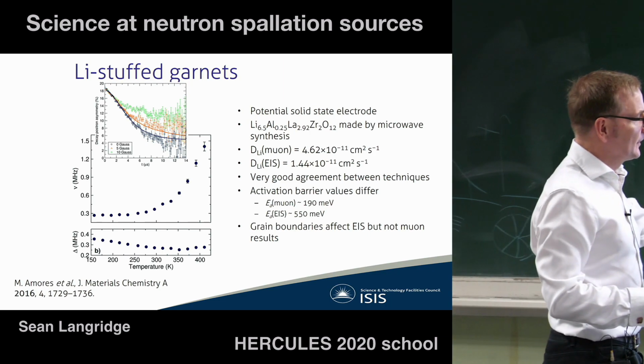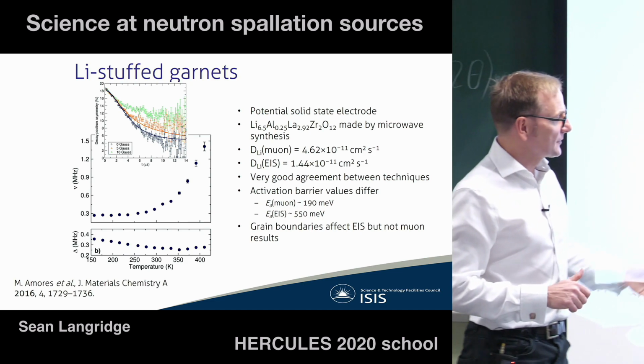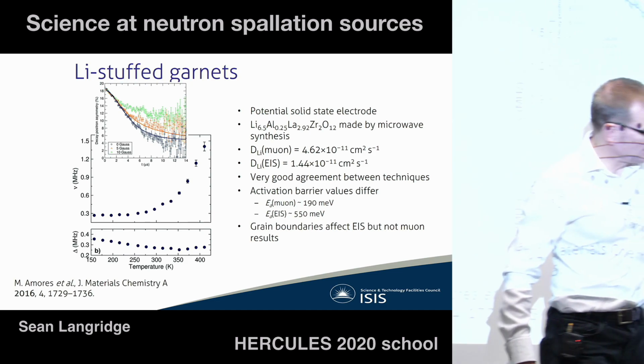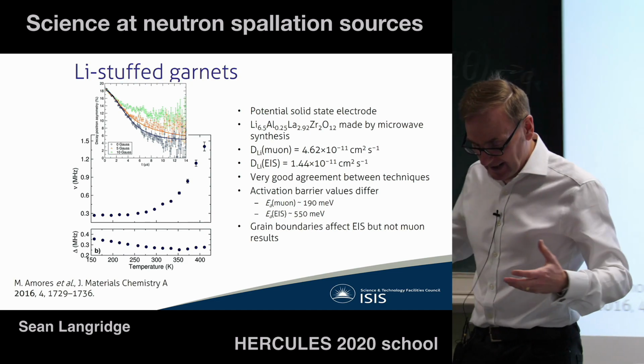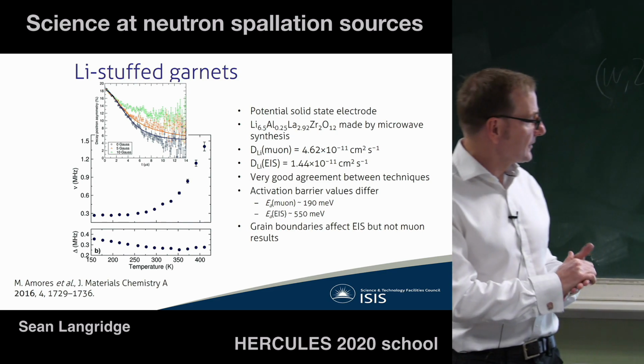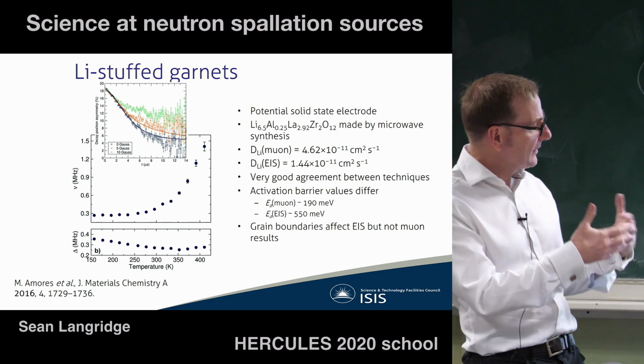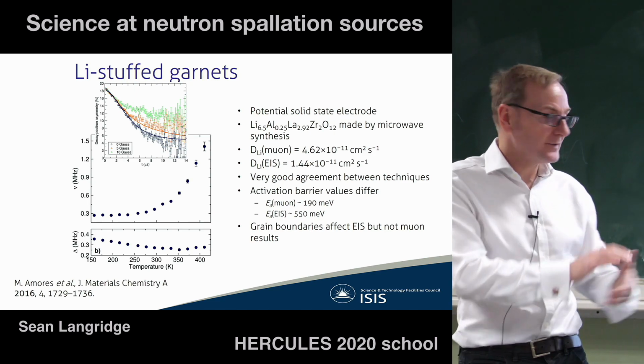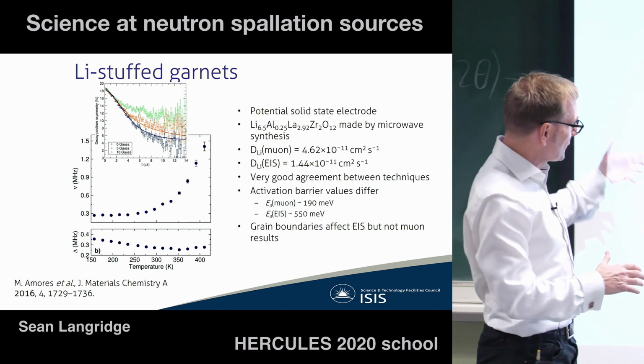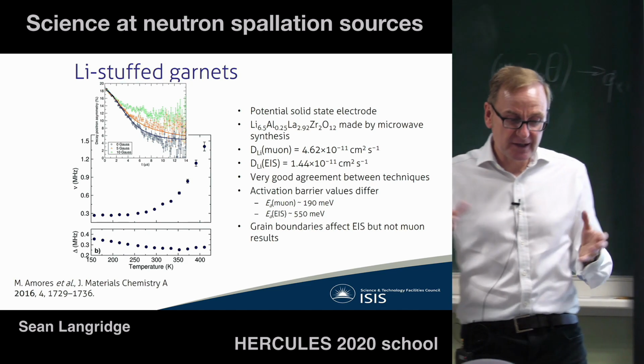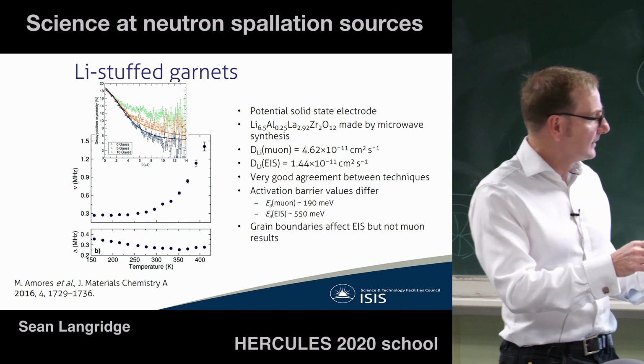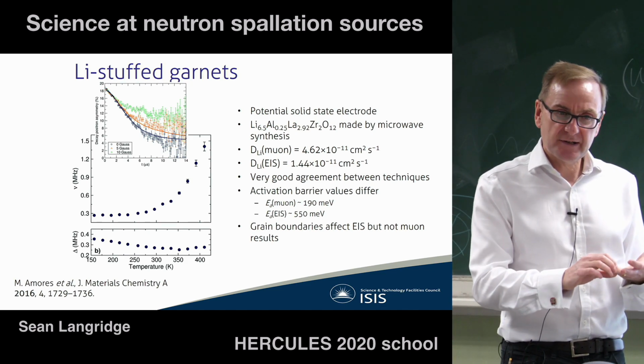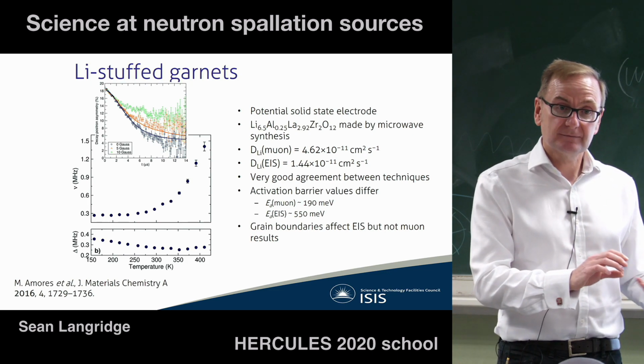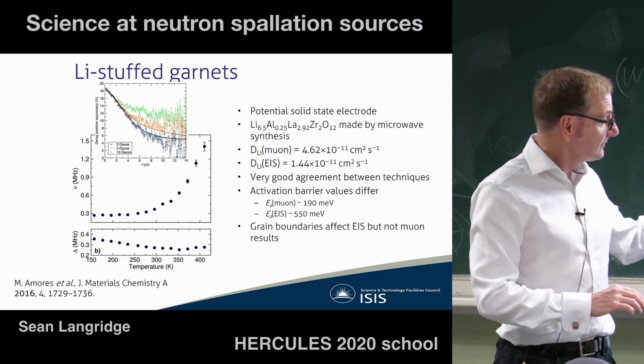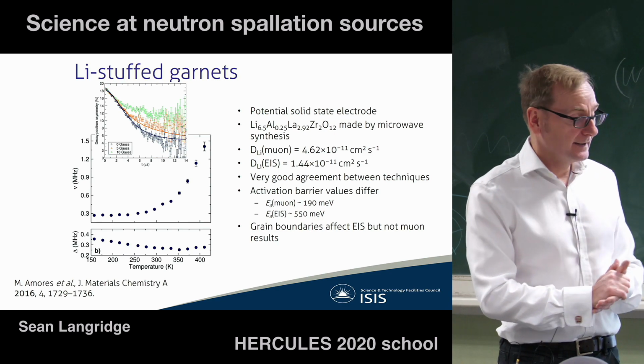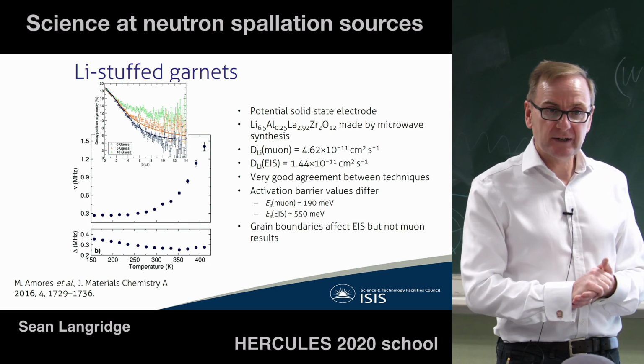And the nice thing with the muon technique is that they don't get affected by things like grain boundaries. Whereas if I understand correctly, if you're doing things like impedance spectroscopy, you have to worry about grain boundaries as your ions diffuse around. Muons are not sensitive to that because it's a local probe, but you can see this ionic diffusion. So very good as an analogous particle to hydrogen in systems, light element diffusion, and very weak magnetism.